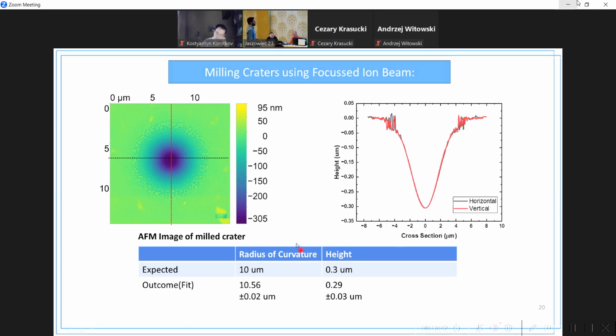This table shows what we input as the parameters for this crater inside the script, and this is what we got as an outcome when we figured out all the relevant parameters for the milling. So this shows that we can control the radius of curvature, height, and the geometry of the crater to a great degree of freedom.